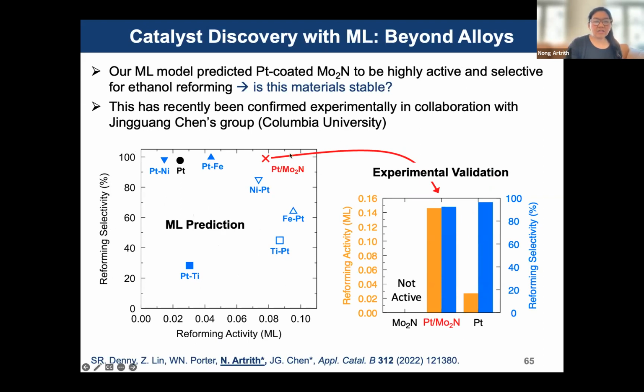And then I asked the collaborator from Jingguang Chen's group at Columbia to check and validate by synthesis and also test the performance. You can see clearly that if they use only molybdenum nitride, it's not active, not as good as other types of catalysts. So this already shows that using cheap molybdenum nitride materials alone is not working, not good in activity, and also cannot get any selectivity of hydrogen production that I want.